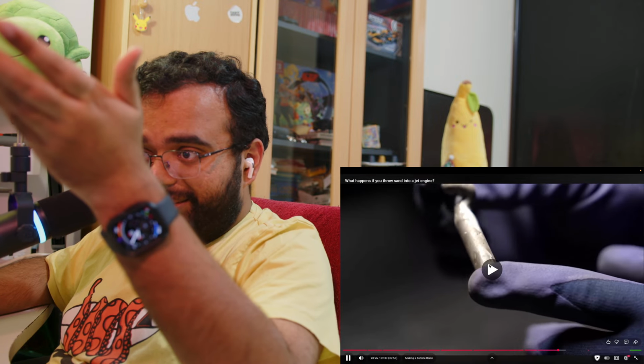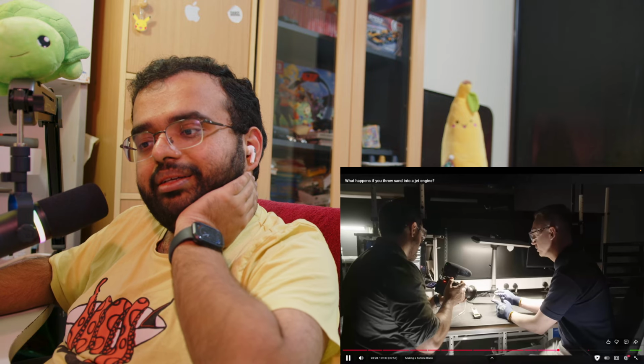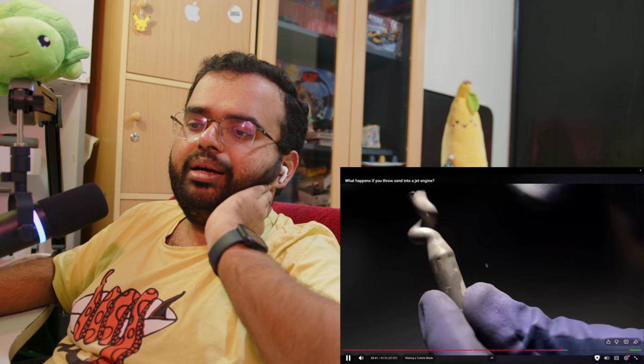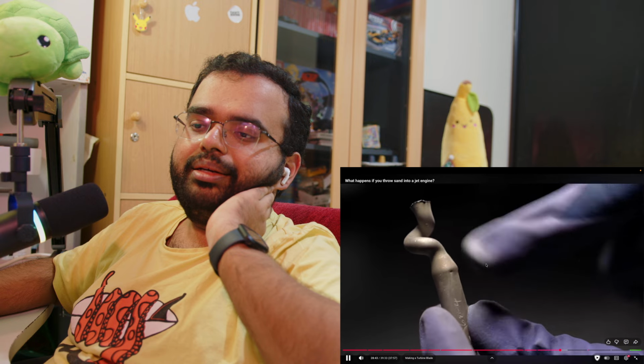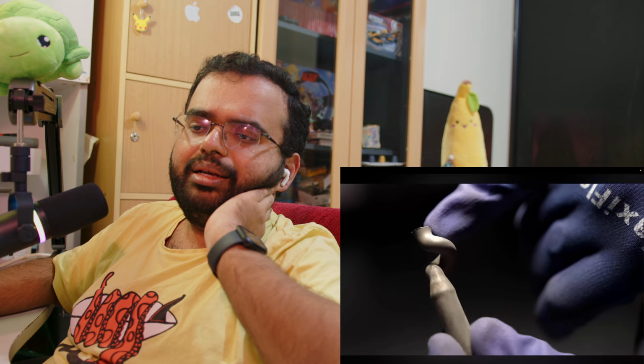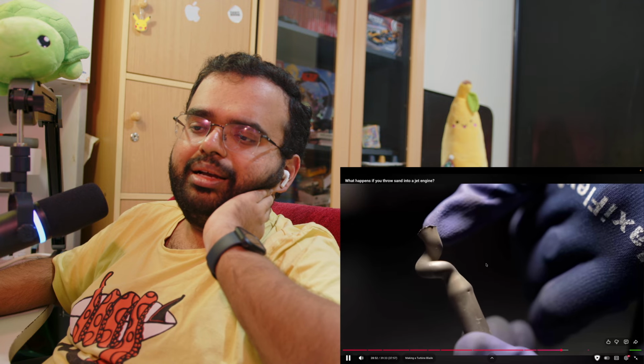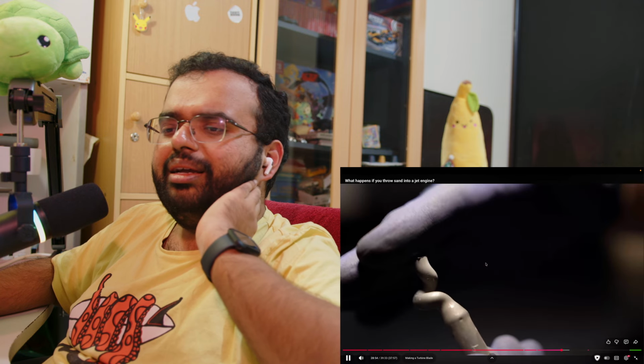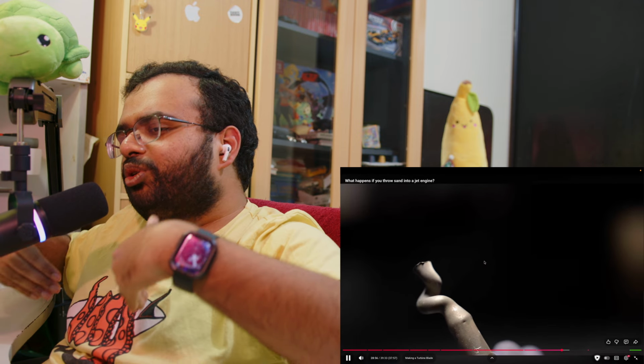That's insane. So this is a starter attached to a spiral that we've etched so that we can reveal that structure. You can see down at the bottom, we are starting to grow directionally solidified grains. But as we go up the spiral, the grains are starting to be choked out by the upper surfaces of that spiral until when we get to the top, we're just a single crystal, and that then allows that single crystal to grow right through the blade.